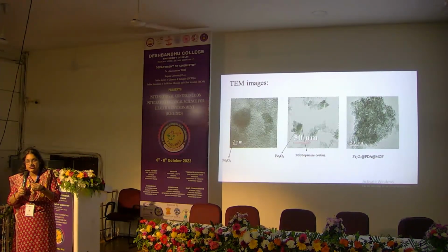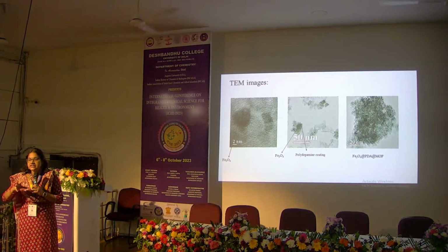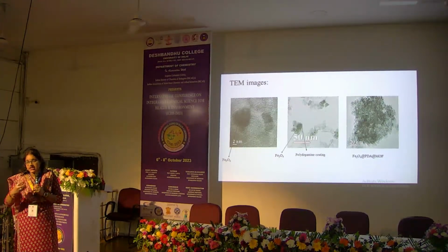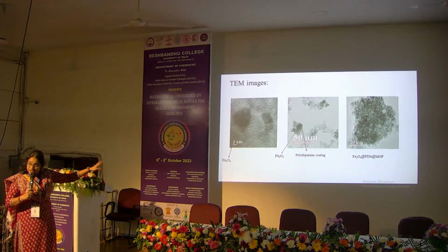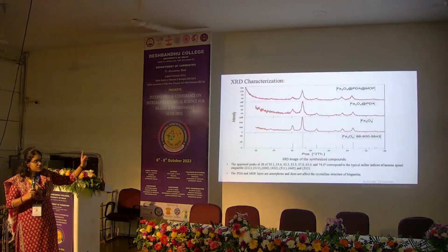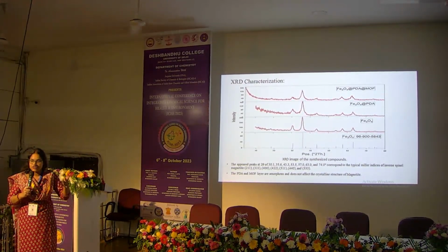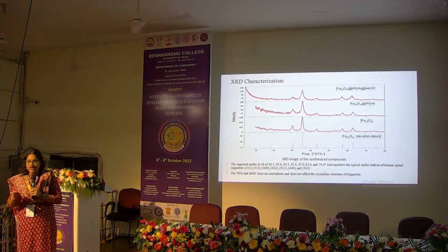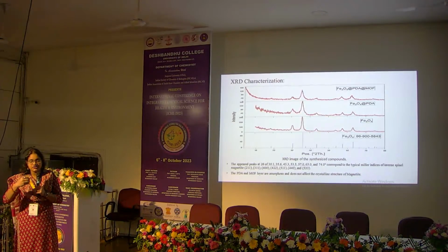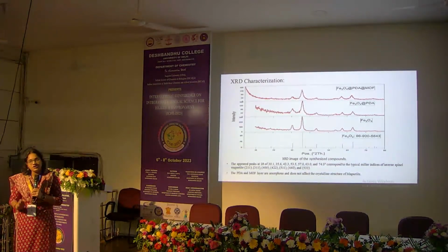It can be of clusters, because as we synthesize magnetic nanoparticles, they aren't completely dispersible. They make agglomerates instantly. I can see your nanoparticles are below 50. Yes, sir, it is below 50. But because of DLS, as soon as I synthesized 2 days before and took the DLS, it agglomerates. I have seen the agglomerates however much I try. Only if I coat it while synthesizing does it remain stable. Otherwise, because I'm completely using water here, it agglomerates instantly.